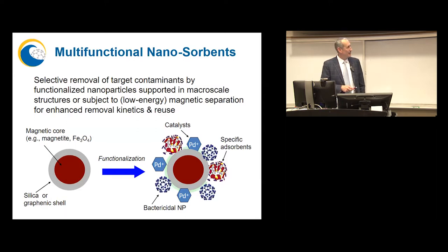But the point is that these superparamagnetic nanoparticles can be decorated with different functionalities, catalysts, absorbents, biocides, and so on, to essentially create multifunctional nanoparticles that are amenable to low energy magnetic separation so that you can capture them and reuse them. And we are testing these for industrial wastewater applications, not for drinking water, because we are committed to never using a free nanoparticle for drinking water just in case they escape.